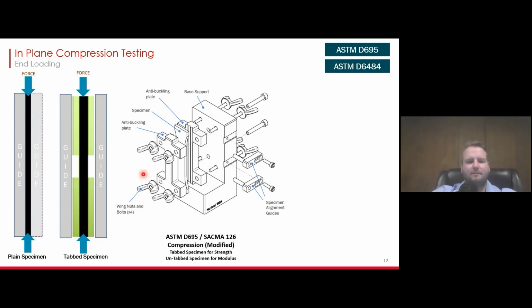You can also run this test with this test fixture with tabbed specimens, which would look something like this. The green parts here are supposed to show the tabs of the specimen, and then you're running a free gauge section down here in the specimen, but still supported by the guides of the fixture. So you can see here the anti-buckling plates, and then your specimen here in between them, and then they get connected to the base support, where your specimen rests on the bottom of the base support, and it will stick out of the anti-buckling plates ever so slightly on the top, where you then apply the load coming down with a compression platen.